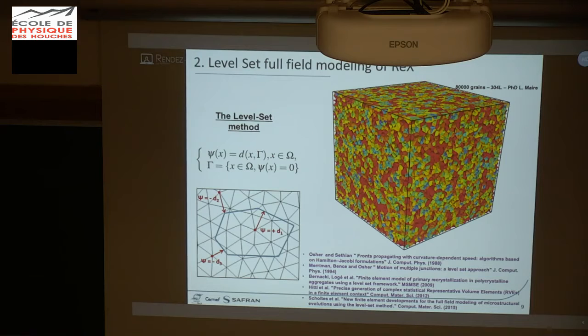And you can see also generally a sign convention. Here we use a positive Euclidean distance inside the object, inside the grain, and a negative distance outside the grain. And finally, the grain is perfectly described by the zero value of the distance function. You have an implicit but discrete description of the grain interface. You don't have any thickness for the grain interface in this approach. You can precisely describe where the grain interface is by using the zero isovalue of the level set function used to describe the grain.